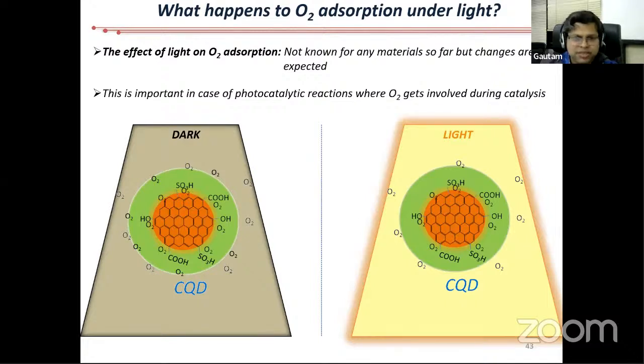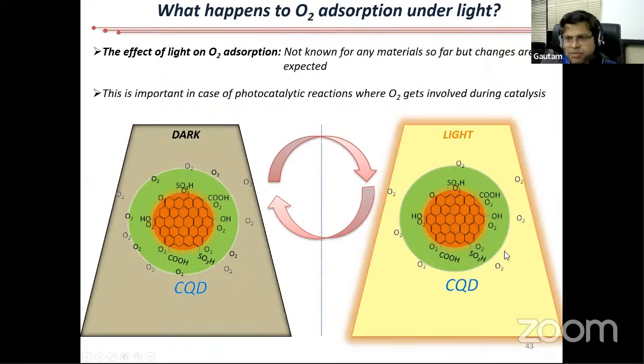All right, this is what I have already explained. And so what we found is that if you look at dark and if you look at light, these are two schematics. You will see very easily here we have many oxygen atoms. But when it is in light, it has a fewer amount of oxygen atoms. And what we have found is that this process is reversible. If you put it in dark, it will again take oxygen. And if you put it in light, again it will release oxygen.